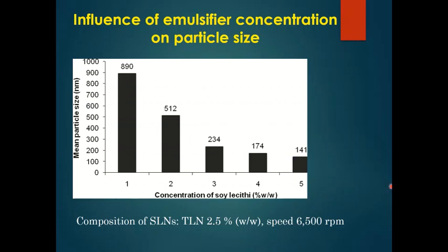What happens is, especially with lecithin, if you use beyond a certain concentration, again there is a chance of increase in particle size. This is because lecithin itself is amphiphilic in nature. So once it stabilizes the surface of the particles, the remaining amount will be in the water, which has the ability to form micelles. So because of the formation of micelles by the excess lipid present, again there will be an increase in size or increase in particle size distribution. So you need to optimize this very carefully, should not use very low concentrations and should not use very high concentrations also.